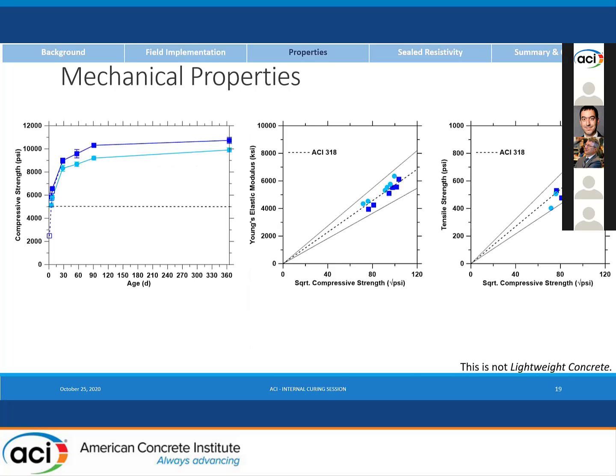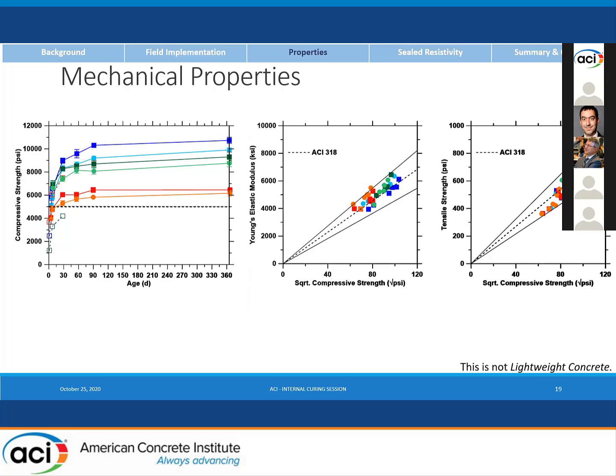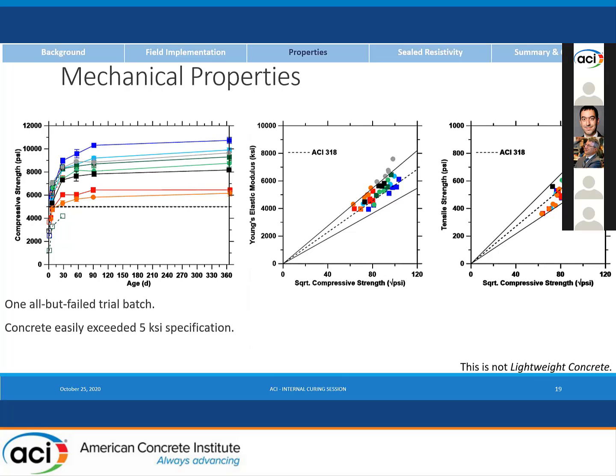Going through the experimental data very rapidly here, we can look at the mechanical properties. We can see that indeed these were all very high strength materials, and in general, the ACI equations within the plus or minus 20% that we would be looking for do indeed apply. So this is not lightweight concrete.